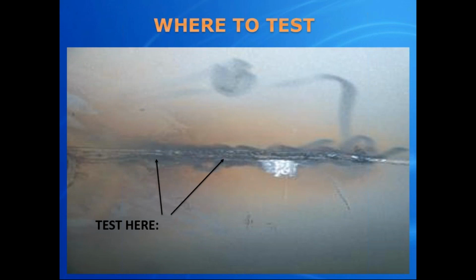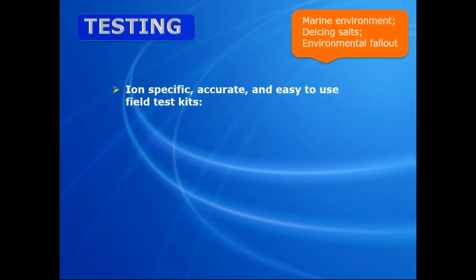The stick rods that are used for welding of the carbon steels are basically inundated with magnesium chlorides and sodium chlorides, which are salts. And I checked around with the welding societies and found out that they put those sodium and magnesium chlorides into the welding flux to be able to get the arc when they're doing the welding process. So what's happening is when they're welding all these pieces of steel together, they're actually contaminating the surface as we see it today. We knock off all the BBs and pop off all the existing flux that we can see and all that. We sandblast to get a profile, but we don't remove the sodium and magnesium chlorides that are embedded into the micropores of the steel. Hence, you have induced corrosion, in fact, and don't even know it.